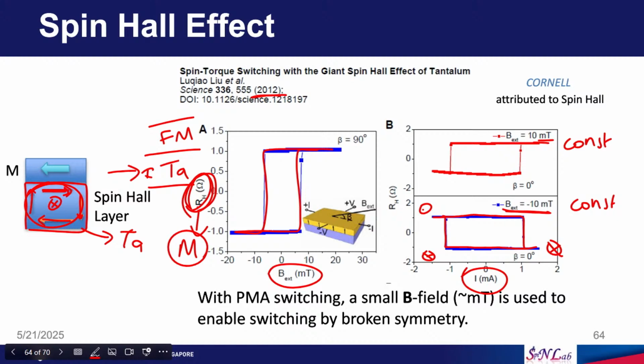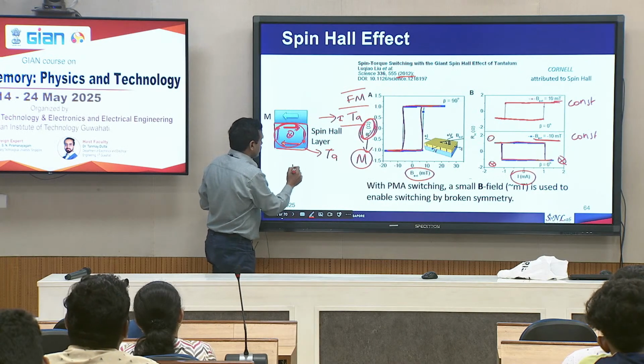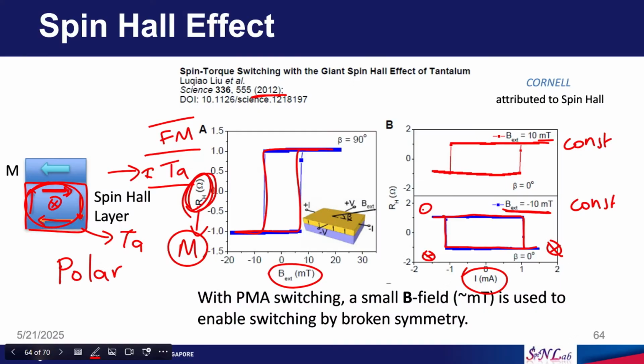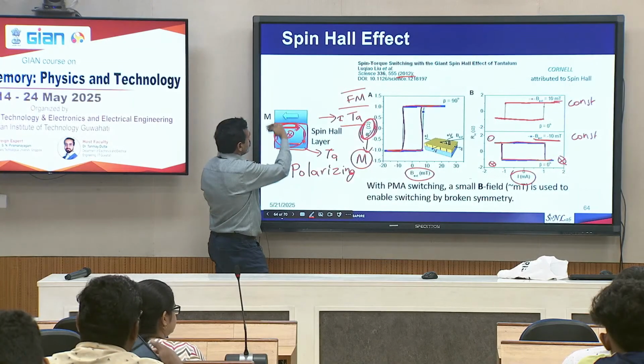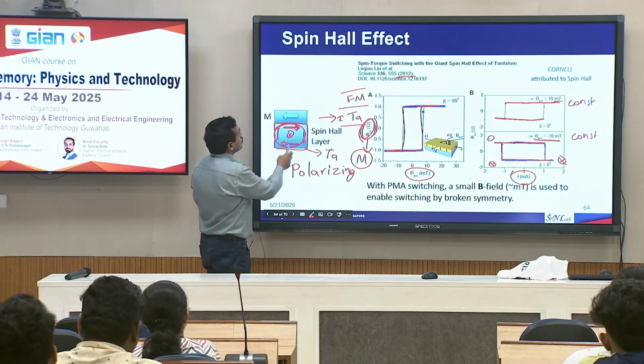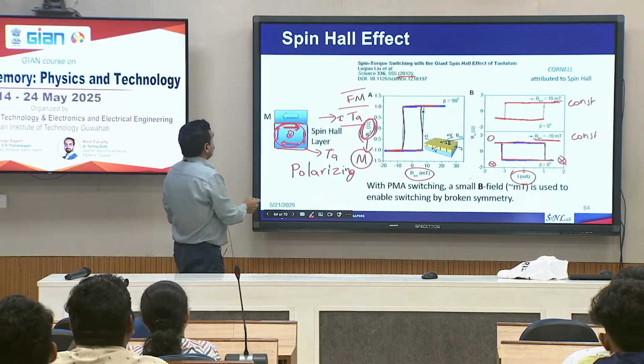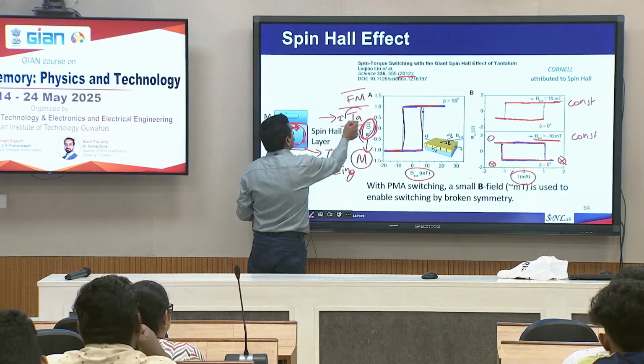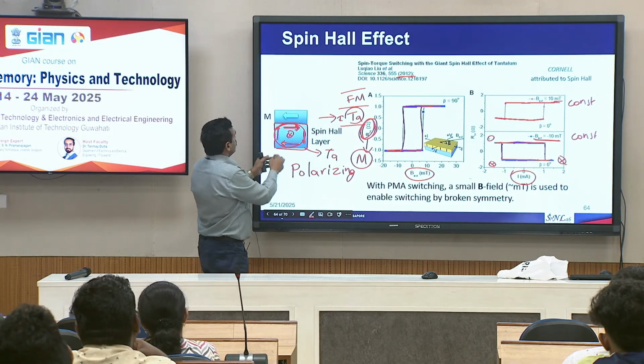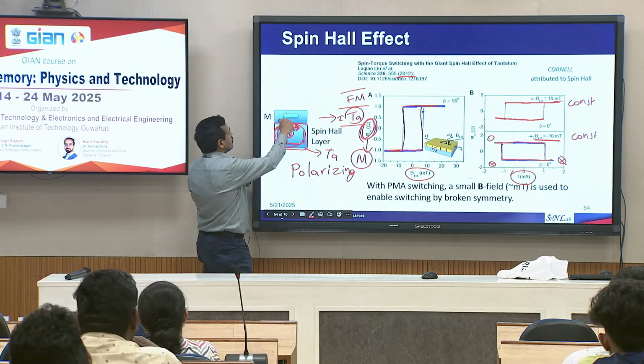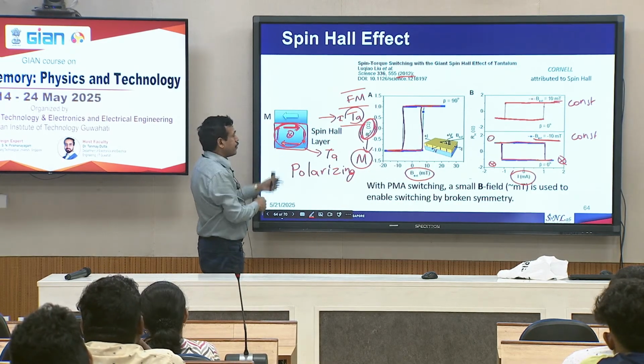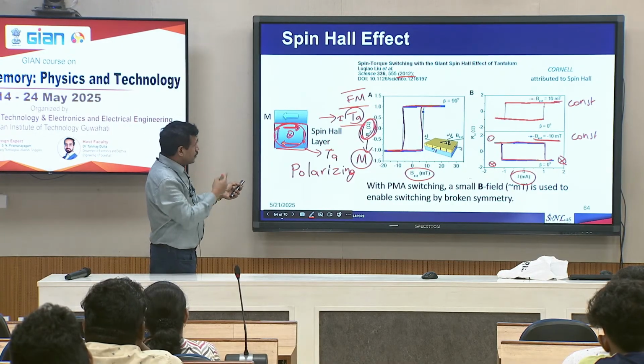So, here you notice that there is no special polarizing layer. In the case of STT MRAM, you had a ferromagnetic layer, that ferromagnetic layer polarized your spins, and because of that polarized electrons you were switching. But in the case of spin Hall effect, you are just using a heavy metal layer like tantalum or tungsten, and using the spin Hall effect you accumulate a certain type of spin which helps to switch the magnetization. Okay. So, this is called spin Hall effect.